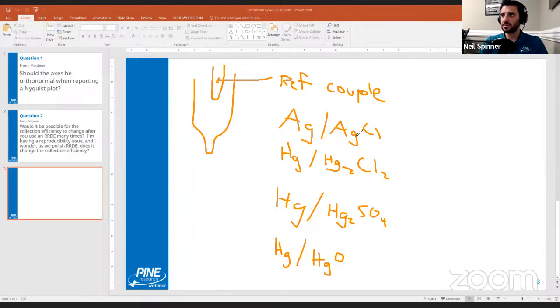Essentially, through the Nernst equation and the concentration of solvent and electrolyte in and around whatever this couple is, whatever this material is, the potential is set. And that's how the potentiostat is controlled. Now, it doesn't really matter what this potential is. So these have different standard potentials. This one's like 200 millivolts, something like that. Calomel is like 220. Mercury sulfate is like 650. Mercury oxide's like 100. So they have different standard potentials, but it doesn't matter. It just means that if you're picking your CV potentials, let's say you're going to start from 0 to 1, well, now instead you're going to start at minus 200 to 800. You're just shifting it. It's all relative. It doesn't really matter what it is, just as long as you know what it is. So that part of it isn't important.